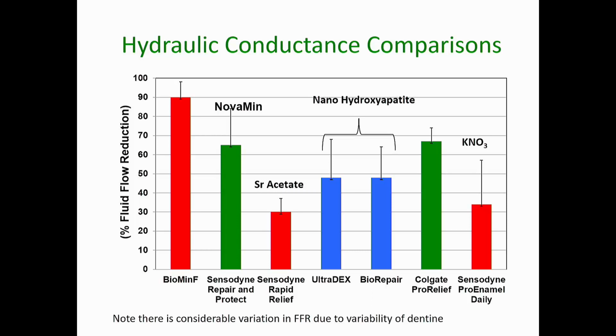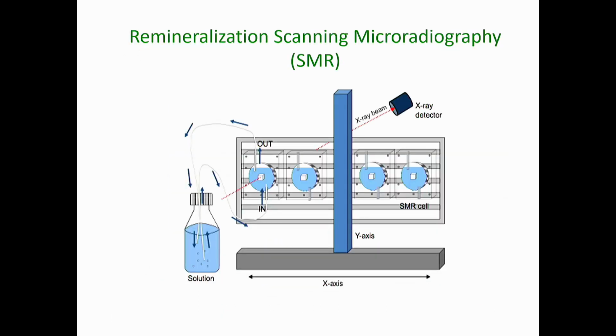And then we have some other toothpastes for comparison. A potassium nitrate one, which you wouldn't expect to occlude dentinal tubules, but contains some silica particles, for example, which do have a tubule occlusion effect. And also some nanohydroxyapatite toothpastes, which are also giving about a 50% reduction in fluid flow.